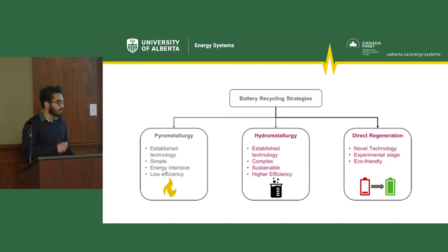And right now there's a concerted effort to move away from pyrometallurgy because although it's simple and relatively easy to implement, it is very energy intensive. It requires temperatures in excess of 1,000 degrees, around 1,200. And of course, a lot of the metal is lost as slag, so this is not the most efficient. The other method is hydrometallurgy. This uses chemicals to achieve metal recovery or reclamation. However, this is a much more complex process that requires multiple steps compared to pyrometallurgy, albeit possessing a higher efficiency. And the third one is called direct regeneration.